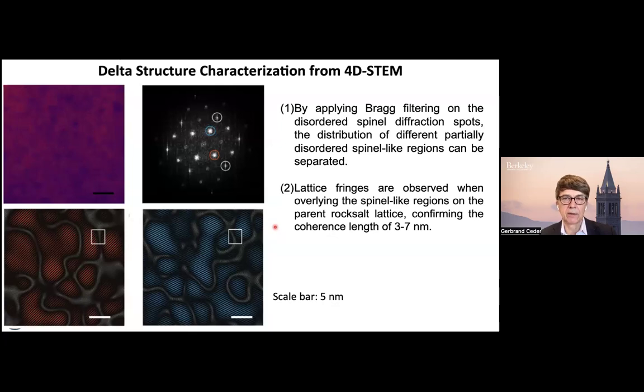If you actually look at electron diffraction, you certainly see new reflections that are reminiscent of spinel. And if you do 4D STEM and you use appropriate Bragg filtering, you see this microstructure. And this microstructure is sort of on the scale of somewhere around 5 to 10 nanometers, and you actually see the lattice fringes. And what these actually are is they are different variants of spinel that have formed from the rock salt. And the boundaries that you see here so beautifully are actually antiphase boundaries between the spinels. So what may be surprising to you, and was certainly a surprise to me, is that if you nucleate spinel from a rock salt, there are 8 distinct variants.